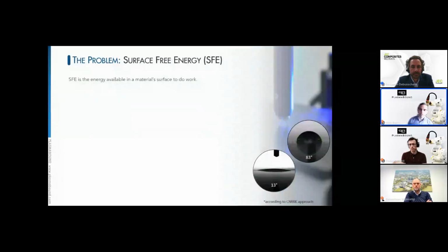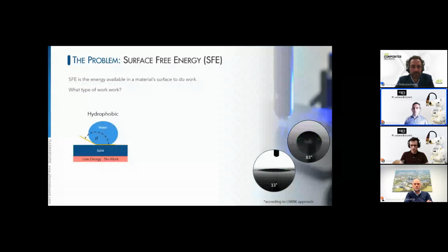So when we talk of a common interface, one of the key properties of an interface is its surface free energy. It quantifies the energy available at a material surface to do work. So what type of work are we talking about? Well, essentially, it's breaking down of a liquid surface tension like water or, for instance, a paste adhesive. So if we look at hydrophobic surfaces where water sits proud, it tends to have a low surface energy. When we have a mid-level surface energy, we'll see the water forming a dimpled droplet. Essentially, it'll sit somewhat proud, but not as proud as on a hydrophobic structure.